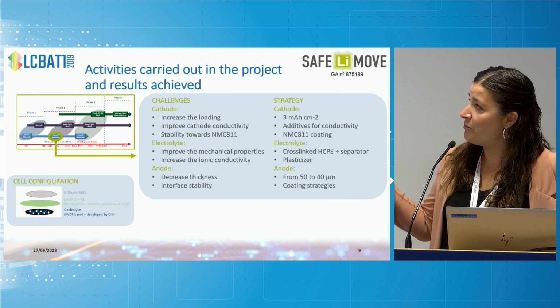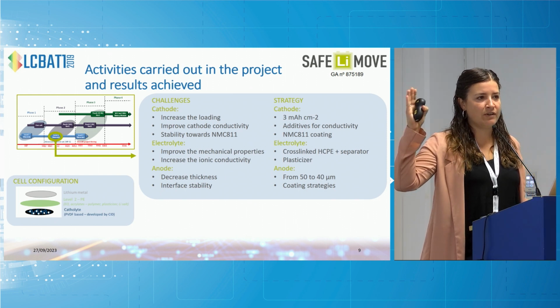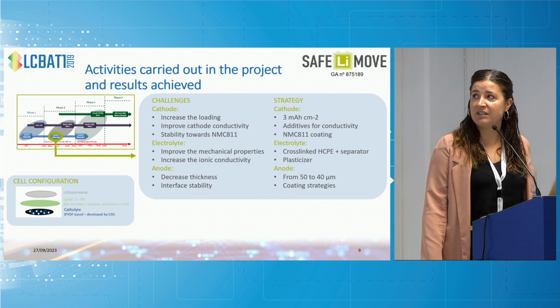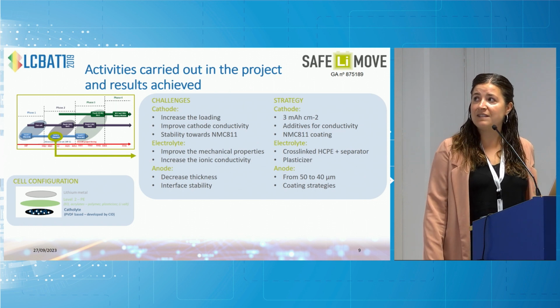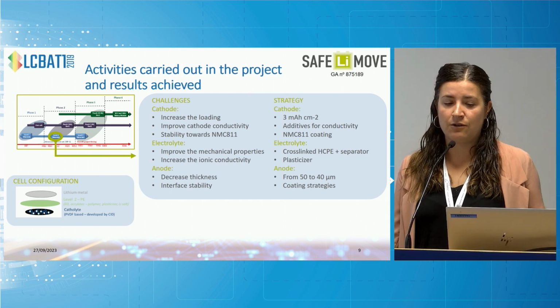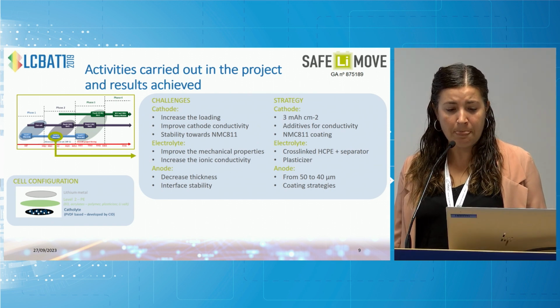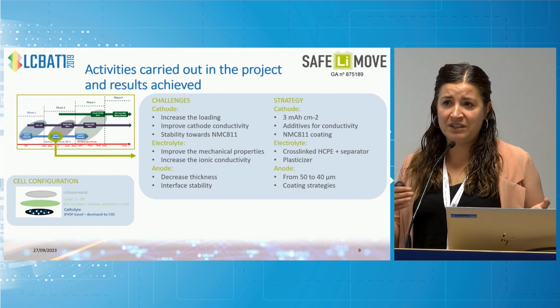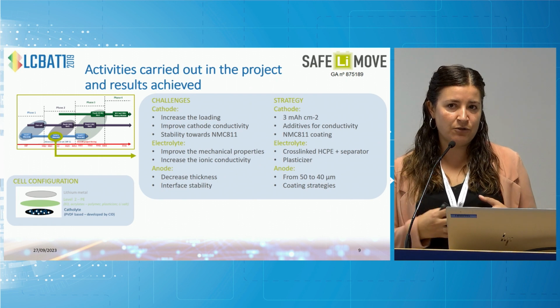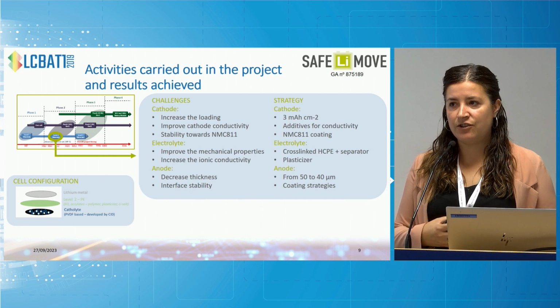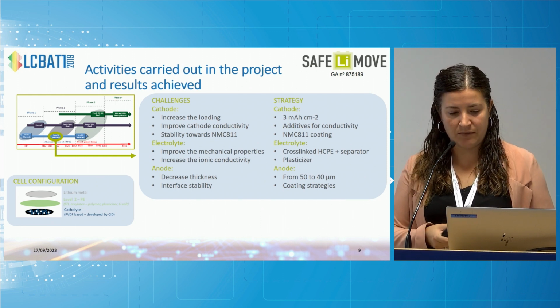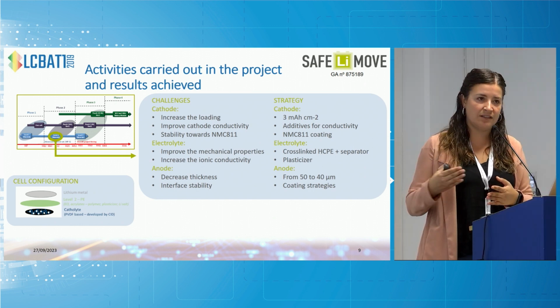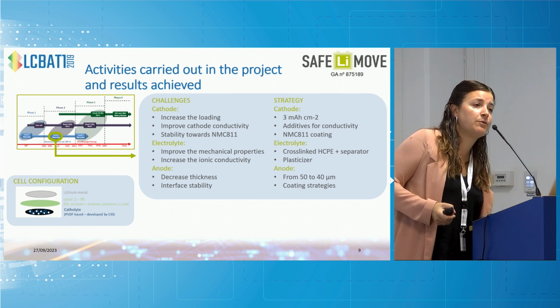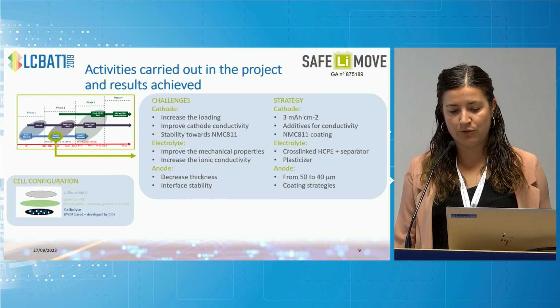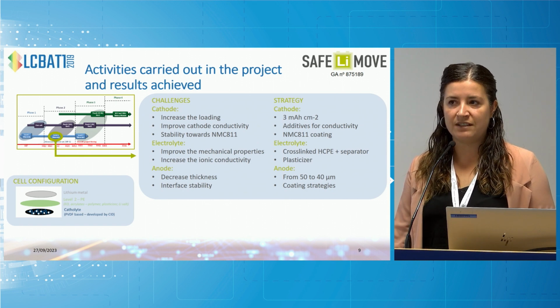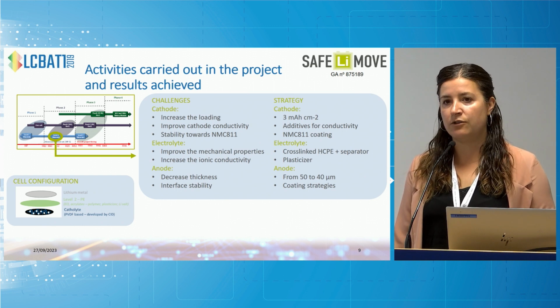So for this, the strategies that we developed, so for the cathode, we decided to go directly straightforward towards a really high loading of 3 milliampere-hour per centimeter squared. We worked on the conductivity through different additives, and then Umicore also worked on the development of different coatings for the NMC 811 active material. In the case of the electrolyte, we needed to improve the mechanical properties, as I was saying before, so we decided to go to a cross-linked polymer network containing the inorganic filler, and also the addition of safe plasticizers, a small amount of polymeric oligomers, in order to increase the ionic conductivity without sacrificing the safety of the electrolyte. And then in the case of the anode, again without any copper current collector, we decreased the thickness to 40 micrometers, and then also there has been some activities taken by AVE on the coating of the lithium metal surface.